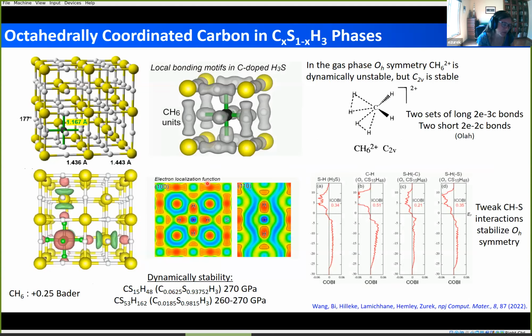So we took a look at different ways that one could dope H3S with carbon. This is one structure that I showed right here, where you have a carbon atom that is going to be octahedrally coordinated by hydrogen atoms. And here's the electron localization function of this atom, showing that you indeed have these types of strong carbon-hydrogen bonds, as well as these more multi-centered SHS bonds.